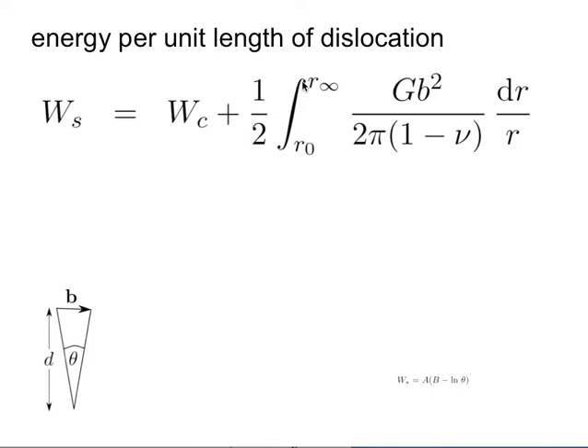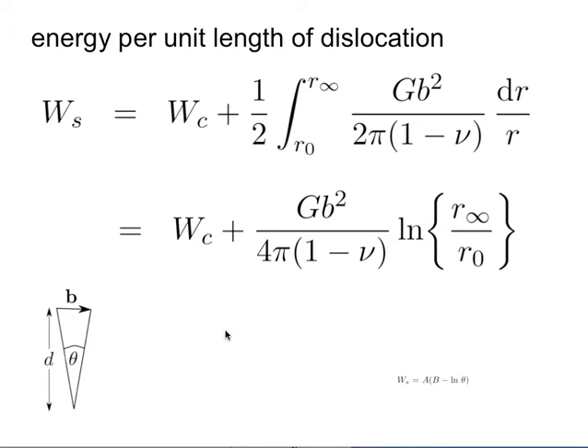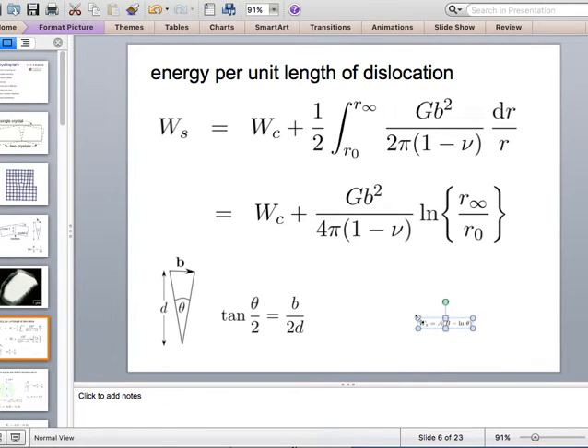But there is a catch. I explained to you that when we have arrays of dislocations, they compensate for each other's strain fields. A vertical array of edge dislocations will have the compression bits and the tension bits aligned. So really the strain field only extends roughly to the distance of the spacing of the dislocations in the array. So R infinity can be set to the spacing d. This is just integrating to R naught, and we can set R infinity to that value. I just need to make this a bit bigger.